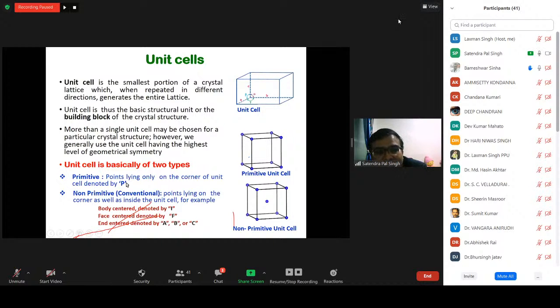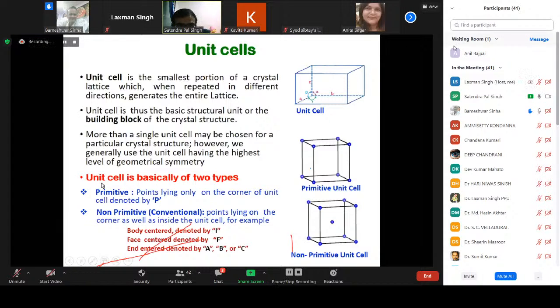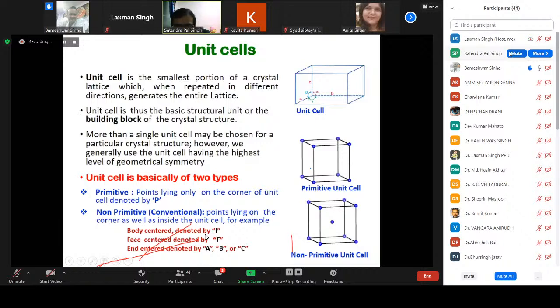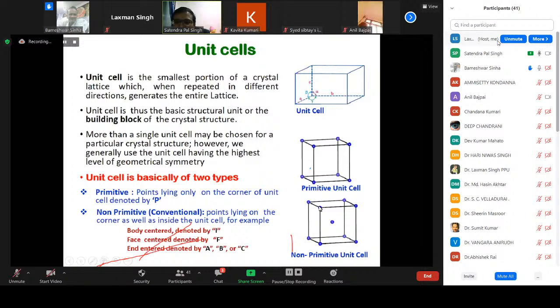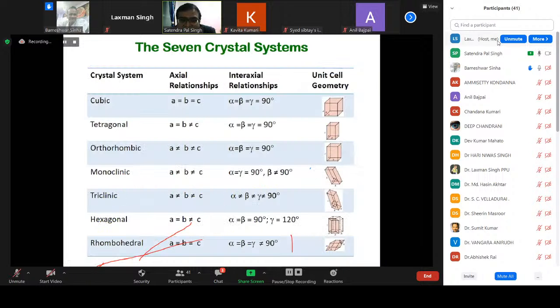The corner-only cell is called the primitive unit cell, and the other is the non-primitive unit cell. That means in addition to the points at the corners, there are also points inside the unit cell. This arrangement leads to body-centered when there is a point at the body center. If there are points at the faces, it is called face-centered, or particular faces like C-centered, A-centered or B-face-centered. So we have different kinds of centering, and this leads to non-primitive or conventional unit cells. This kind of arrangement is classified into different crystal systems, and there are 7 of them.